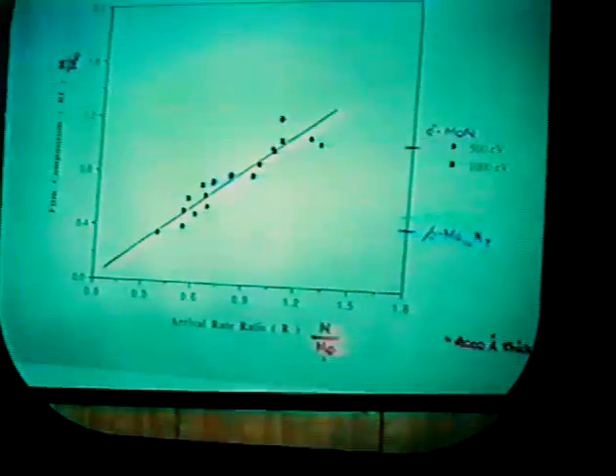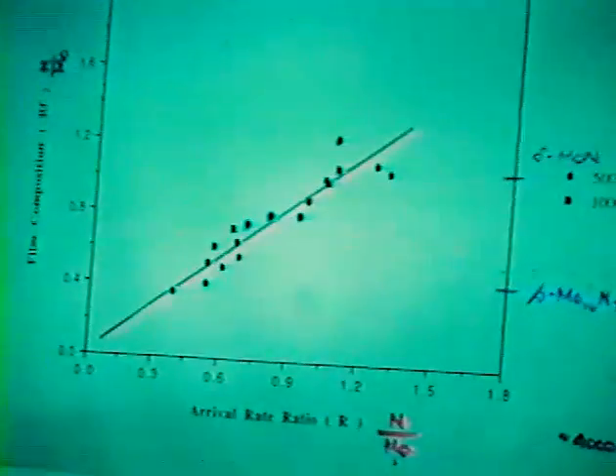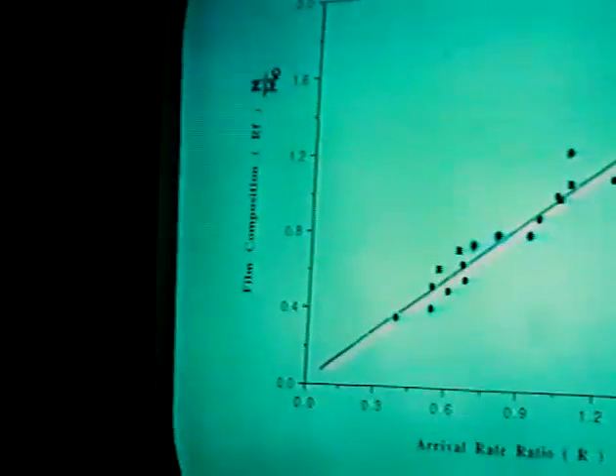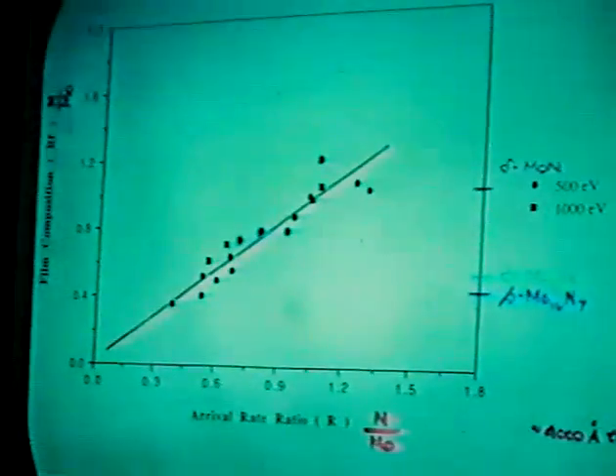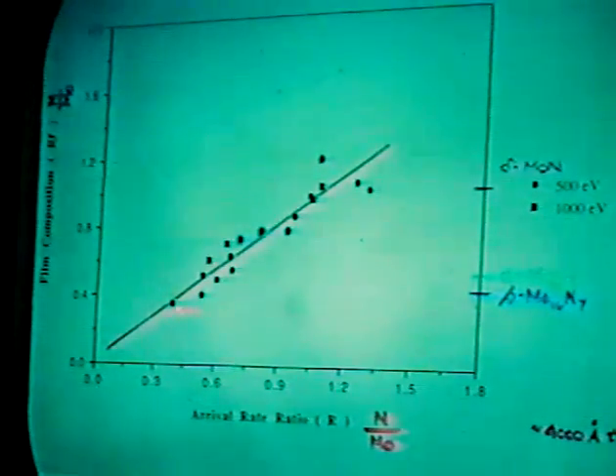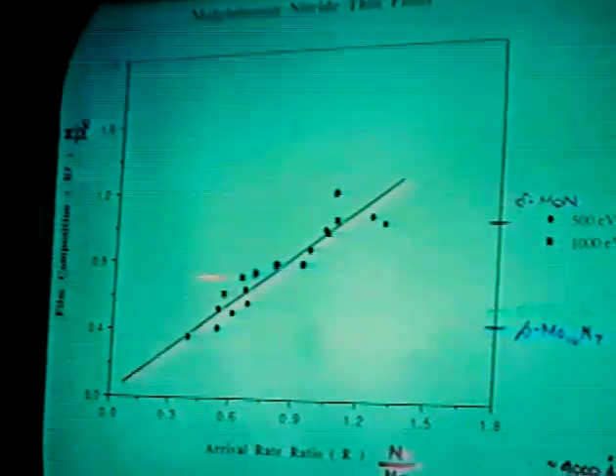Here we use a technique called ion beam assisted deposition. It basically allows us to co-deposit the atoms of interest. In this case, we co-deposit molybdenum atoms while we simultaneously bombard the surface with low energy nitrogen ions. The bottom line is that we can control the stoichiometry, and by controlling the stoichiometry, we can in some cases control the structure, as I'll show you on the next slide. There is a strong correlation between the film composition, which is determined using Rutherford backscattering spectrometry, and the arrival rate ratio, which is basically the flux of nitrogen ions over the flux of molybdenum atoms. And you can see that there is a more or less linear relationship between the two of those.